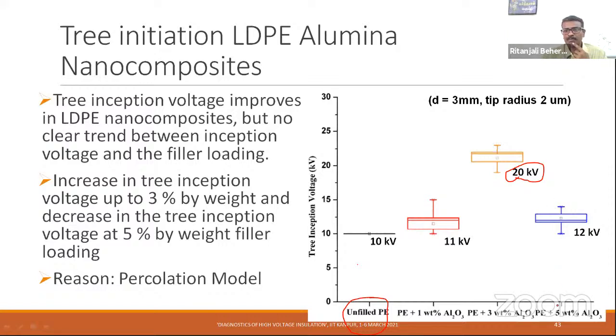And when it becomes 5 weight percentage, it suddenly dropped down to 12 kV. So this tree inception, though it improves significantly from 10 to 11 to 20 kV when the filler concentration is increased up to 3%, drops down to 12 kV when it is increased to 5%. The reason actually could be due to the percolation.